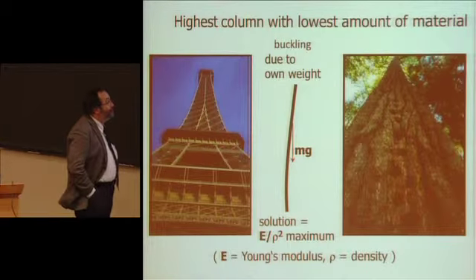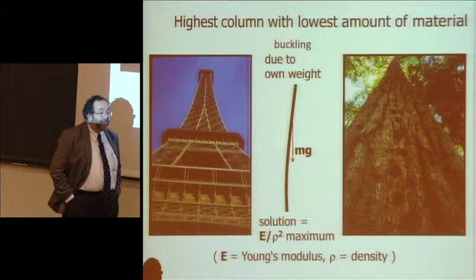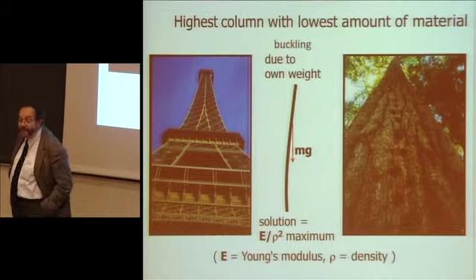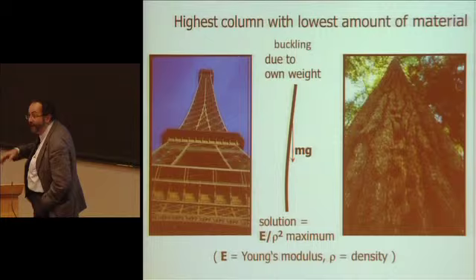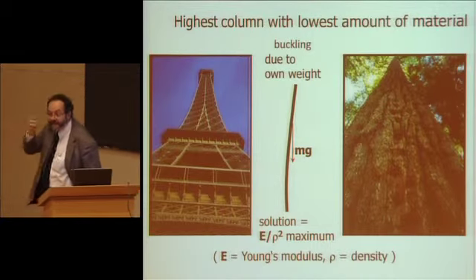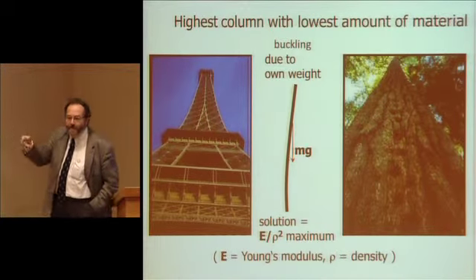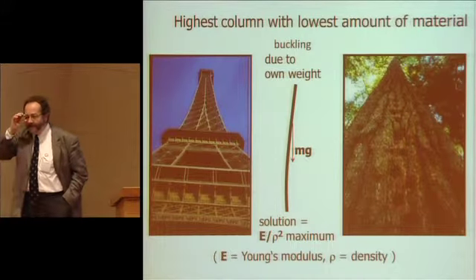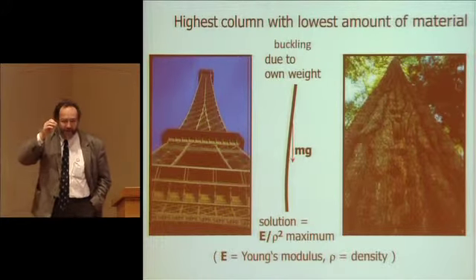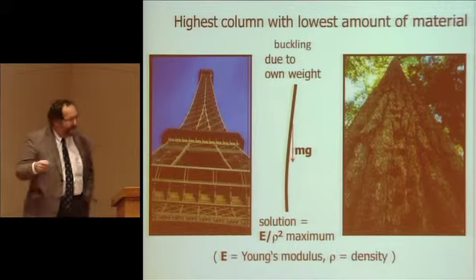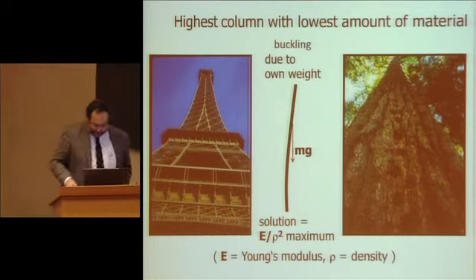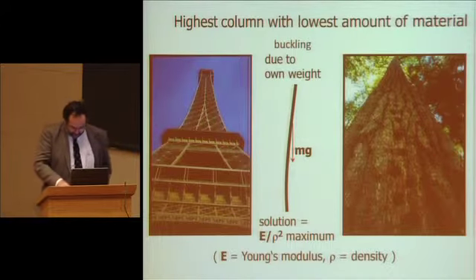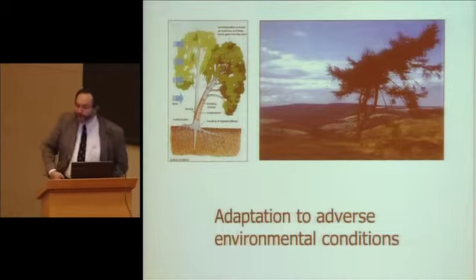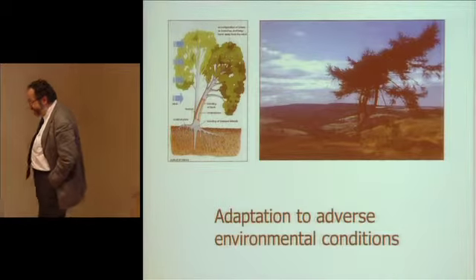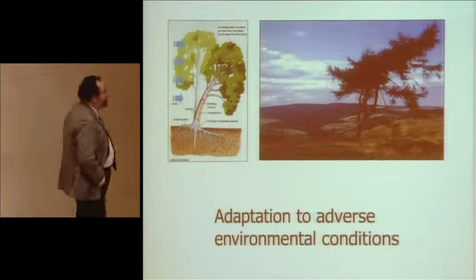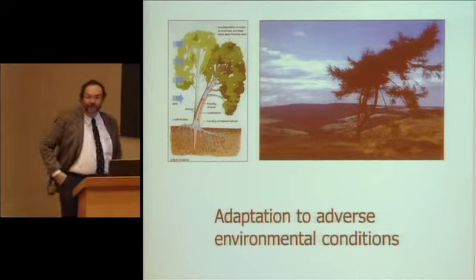So the result is to say we need to find a material where the root of the elasticity modulus divided by its density is maximum. You want to go as high as possible with a column structure which must not buckle under its own weight, which very quickly brings you to the fact that the best material to make a tree is probably wood, which is not really much of a surprise. But one thing that's interesting is that you may imagine a tree growing.